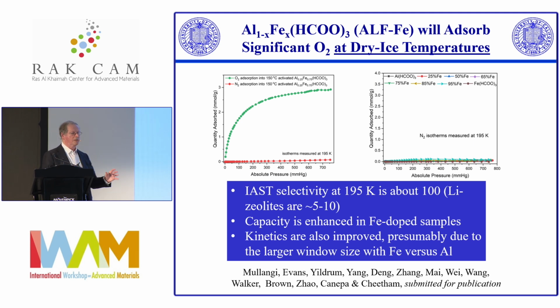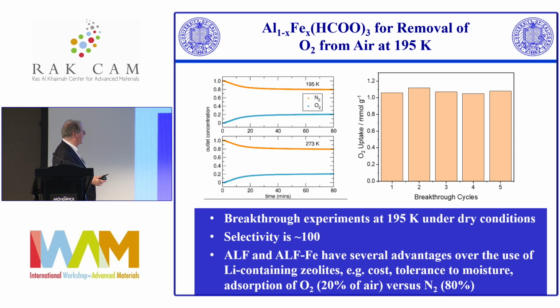So the kinetics was slow with the pure ALF, so what we did was make solid solutions and expanded the lattice a little bit by doping with iron. And that does two things. It actually improves the capacity a bit, and it also improves the kinetics by a factor of 3. We've studied this in exquisite detail, all sorts of different compositions. And for example, however much iron you put in, nitrogen adsorption remains negligible. With Zhao Dan's group in Singapore, we've done breakthrough measurements, using mixed gas, of course, and this confirms what we saw with our adsorption isotherms.